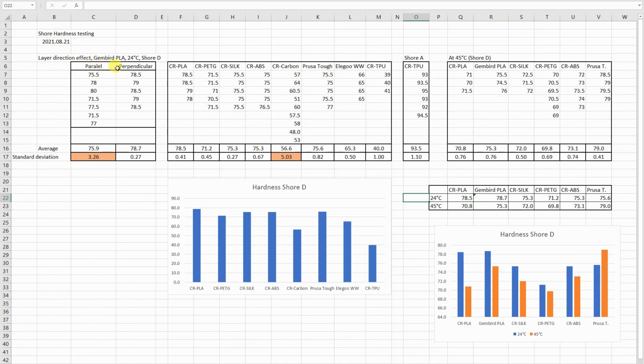In the first experiment I tested parallel and perpendicular to layers, and I can see that if I test parallel to the layers I get smaller values sometimes, but that's not a bigger problem. A big problem is the standard deviation. Everything above 1 is a little bit problematic, and the reason is that sometimes the indentor hits between two layers. So definitely if you want to measure plastic, always measure perpendicular to the layers for better accuracy.